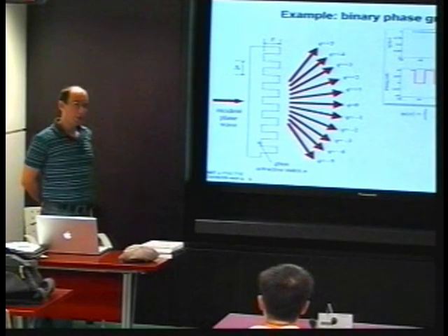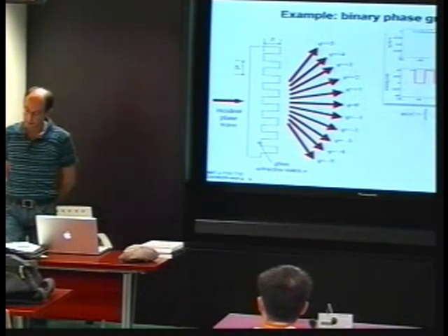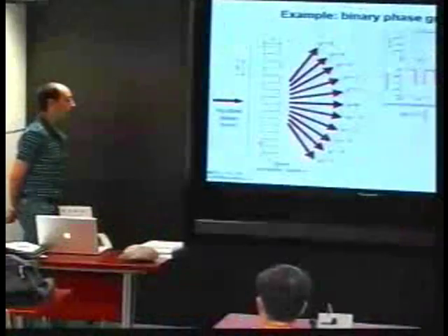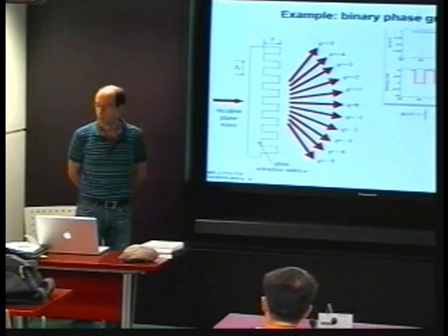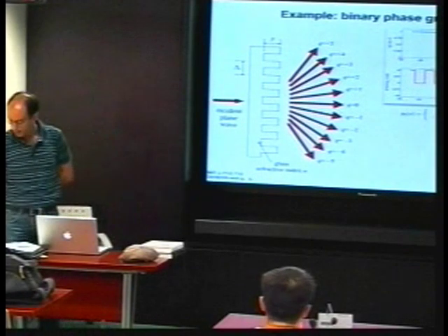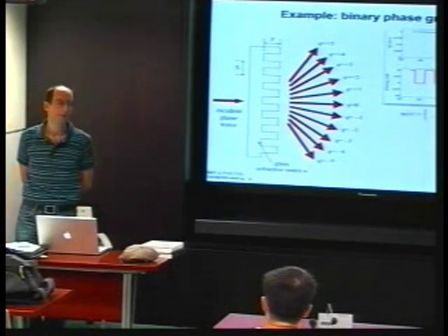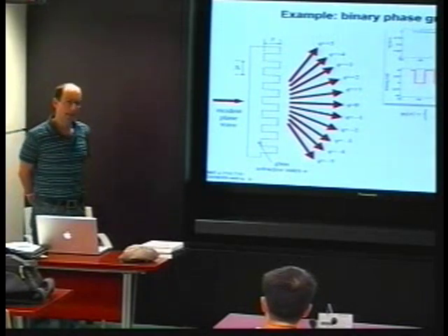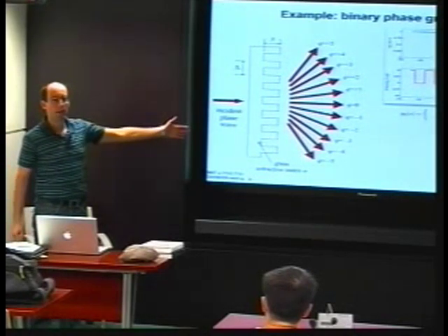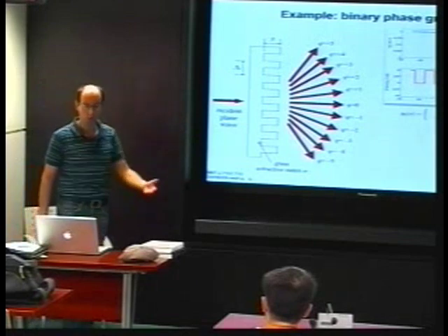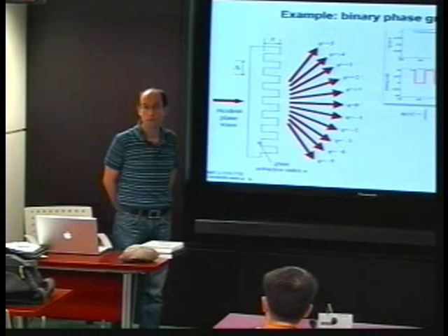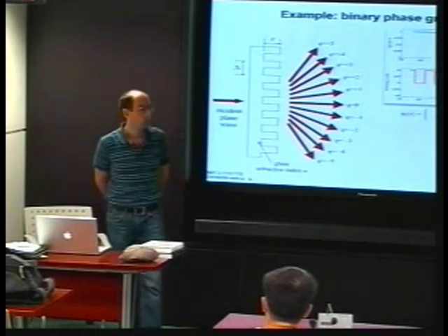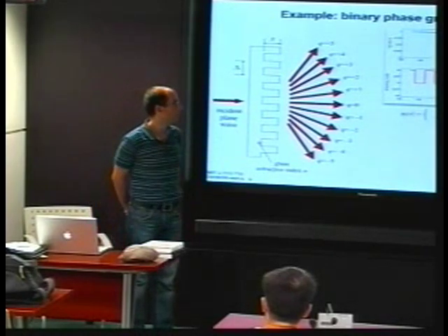With electron beam, you can actually get very small gratings. If it is completely periodic, then people can make something like 100 nanometers or less, easily. So what I mean by 100 nanometers is that this period over here might be 100 nanometers, even less actually. Of course, for visible light, that would be a sub-wavelength grating, and it wouldn't do much, but it could be useful, for example, for ultraviolet light, or for other applications where you don't use it as a grating.